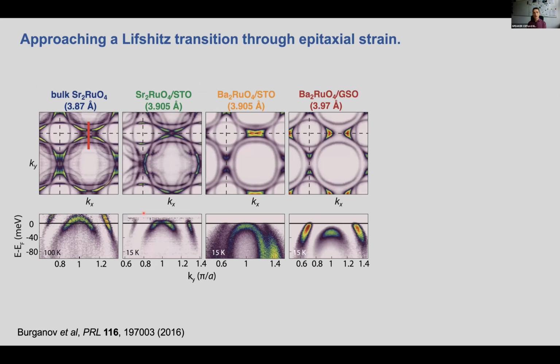Similar work has been done by the group of Kyle Shen at Cornell. So this is approaching this Lifshitz transition through epitaxial strain. So here is bulk strontium ruthenate. There are some extra Fermi surfaces visible due to surface reconstruction, but the key one is here. This is the gamma sheet, and we can see that we're well short of the Lifshitz transition.